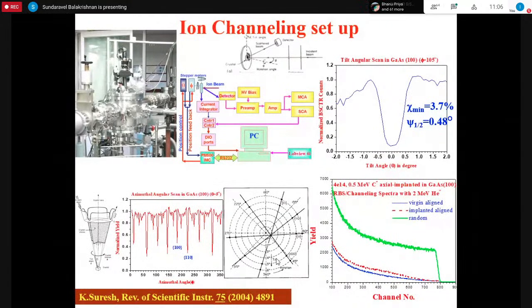For example, this inner circle, whatever is the first circle, corresponds to theta equal to 1 degree, and phi varies from 0, here 90, 180, 270, 360. So this corresponds to 1 degree theta. Next one is 2 degrees, 3, 4, here 5 degrees. Since we kept the angle at 5 degrees, these dip positions we mark. So 8 prominent dips are there.